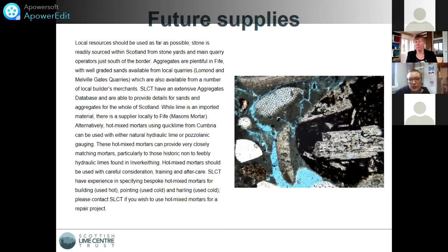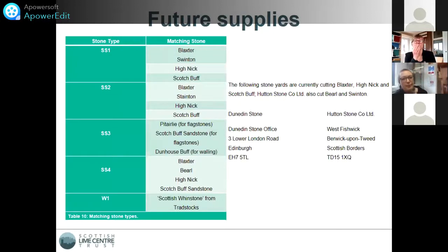And the image on the right hand side is just another image of a mortar sample under the microscope again, and we can provide you specifications and ideas for replicating mixes based on this kind of analysis. And for stone samples, at the moment, there's sadly not very many places in Scotland that are quarrying sandstones, but there are a lot in Northumberland, in the north of England, which are very similar deposits. They're all of the same age and the same deposition type as the ones we have in Scotland. And there's some details of the suppliers here. A lot of these stones are quite similar in appearance when you see them in hand specimen, but it's always a good idea to get samples from the quarry to see what bed they're working at that time.